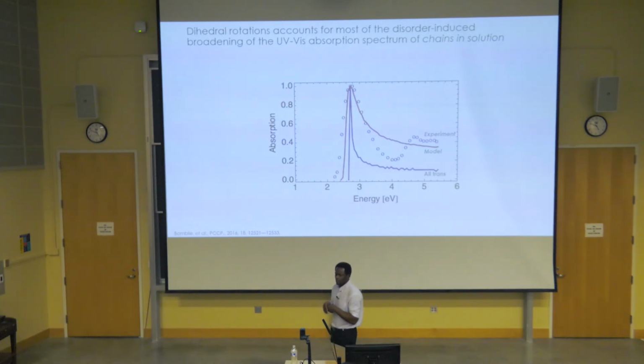It wasn't there in gas phase and melt, so there had to be some sort of connection to the solvent, right? That was what I thought was curious. Yes, there could be some sort of connection with the solvents, and this illustrates why it is important to actually look at what the dihedral distribution will be like for the chain in a medium, and not just translate a dihedral distribution from chains in the gas phase or in an amorphous melt to the solution.